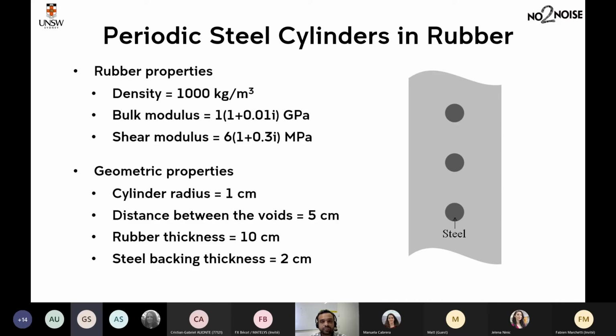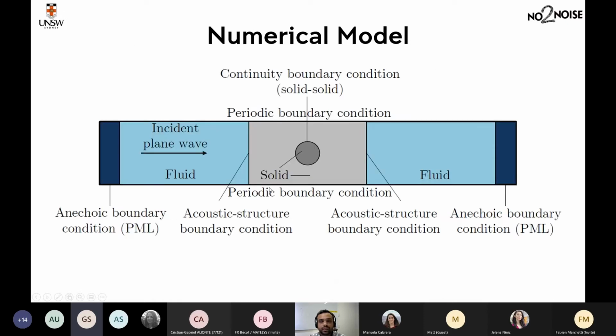Let's talk about hard inclusions now. Again, we just have a layer of hard inclusions, hard cylinders in a soft medium with water backing or steel backing, right? These are the material properties and these are the dimensions. I think I have already talked about this before. These boundary conditions, like the anechoic boundary conditions and acoustic structure condition, remain the same as for a voided rubber coating. The only thing which is different here is that instead of a void or vacuum, we now have a solid inclusion made of steel. And here to model this, we define what is called a continuity boundary condition. Both domains are solid domains.